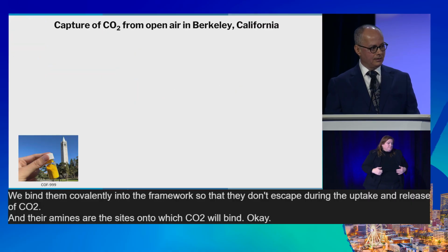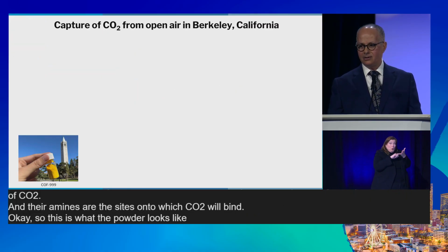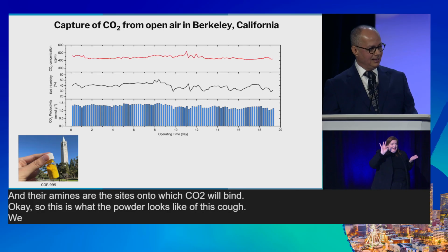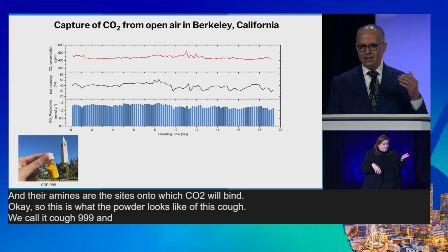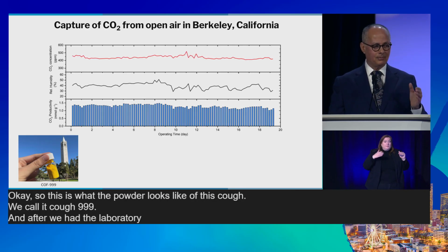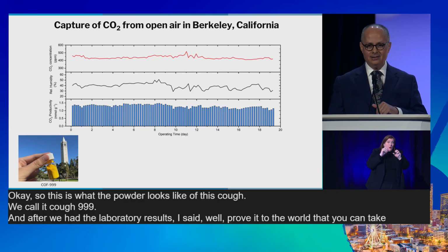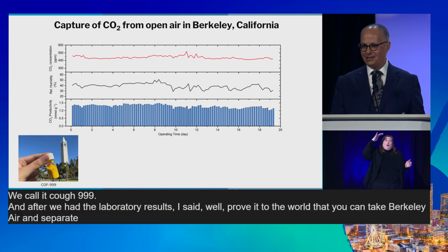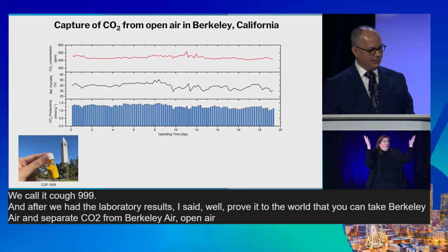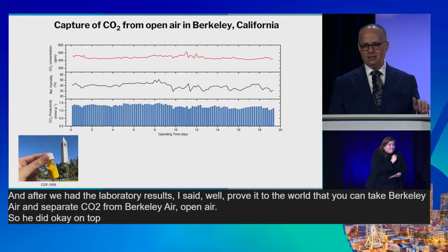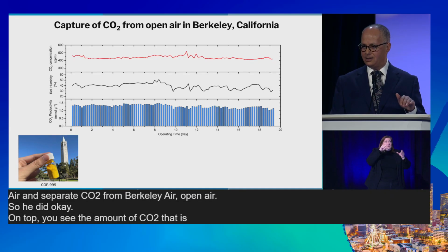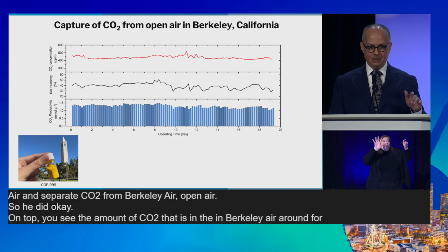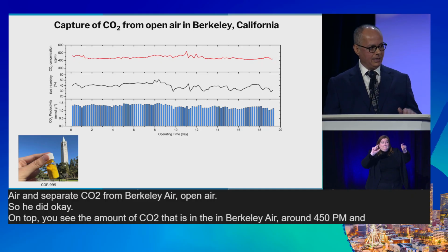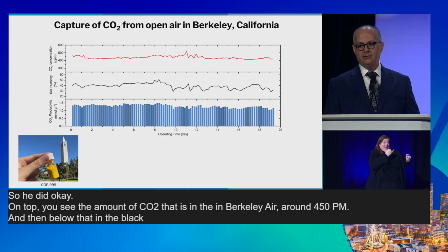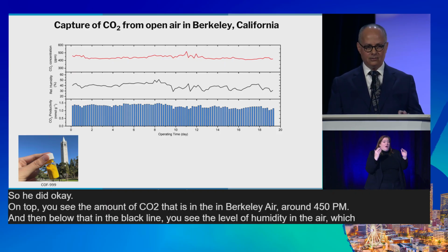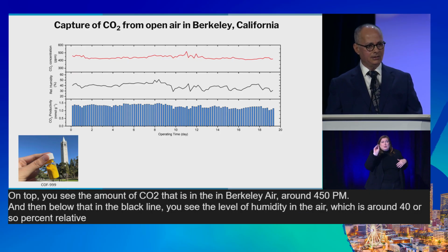Okay, so this is what the powder of this COF looks like. We call it COF-999. And after we had the laboratory results, I said, well, prove it to the world that you can take Berkeley air and separate CO2 from Berkeley air, open air. So he did. On top you see the amount of CO2 that is in Berkeley air, around 450 ppm. And below that, in the black line, you see the level of humidity in the air, which is around 40% or so relative humidity.